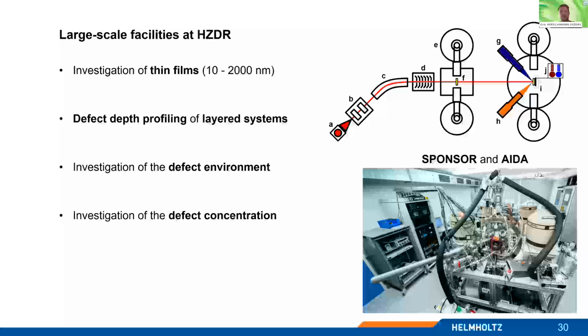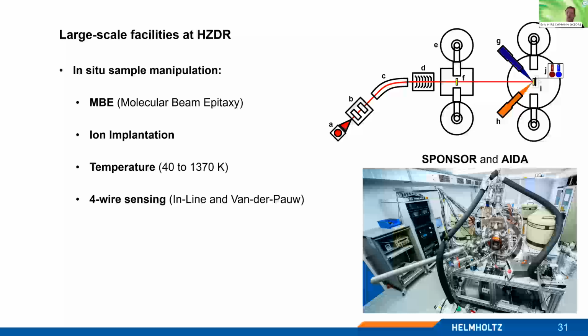You can do depth profiling, so you can also investigate layered systems. You can investigate the defect environment, as I said, using the W parameter, and also the defect concentration. For the apparatus for in situ defect analysis, we have some extra beams within. For example, we can use MBE, molecular beam epitaxy, and ion implantation. We can vary the temperature up to even higher values, up to 1370 Kelvin. And we can also do 4-wire sensing in situ during the positron annihilation measurement.